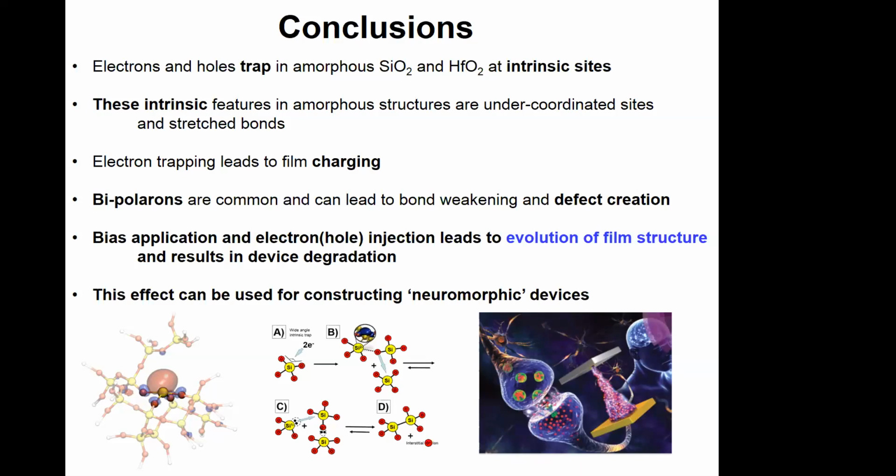This is to some extent similar to what is happening, for example, at surfaces and in the bulk of materials of this type. In some materials, like magnesium oxide, there are no polarons in the bulk. But if you look at nanoclusters of these materials, there is deep trapping of electrons and holes on the surfaces of these clusters because of low coordination of atoms.